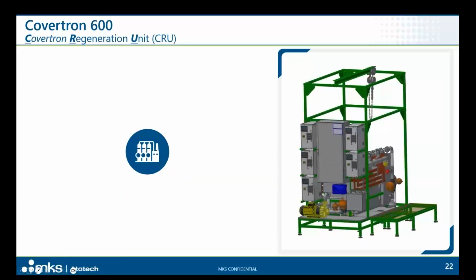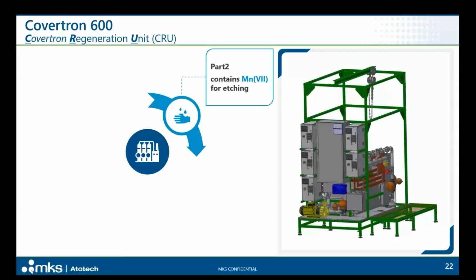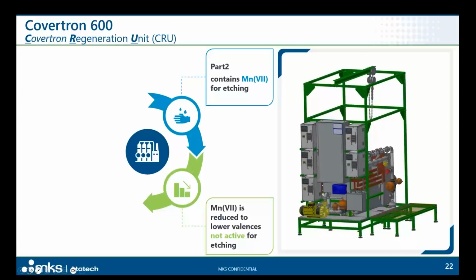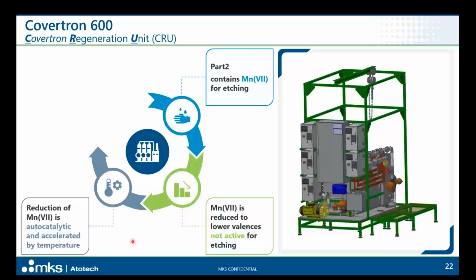So we talk here about the Covertron Regeneration Unit, and at a glance, again, to mention that part 2, the one containing the manganese 7, is what we add with our Covertron 600 additive package. This will, of course, work with the plastic substrate, and the manganese 7, which is coming with part 2, will be reduced to a lower valence, becoming not active for etching. So we need to consider that this reduction of the manganese 7 will come from the oxidation of the resin, but also as a consequence of an autocatalytic reaction, which will be accelerated by temperature.